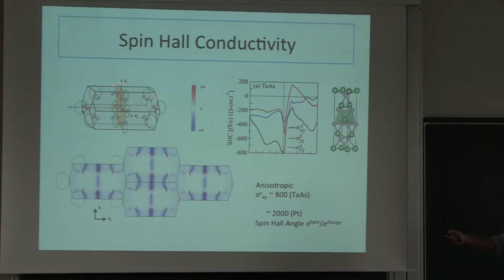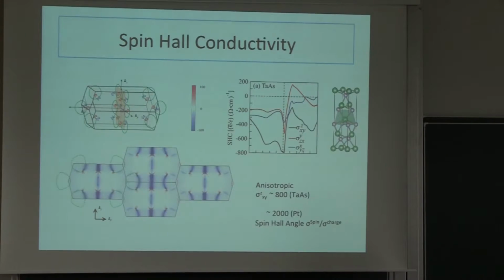And then this is our numerical calculation based on the Berry curvature. What we did is we start with this ab initio band structure information and the wave function. Then we get the Berry curvature. We calculate the spin Hall conductivity directly, and this is the nodal ring you remember. This is the distribution. I just made a projection to some YZ plane. You see clearly that this strong blue color and this strong red color are all distributed around this original nodal ring, exactly because of the band inversion.